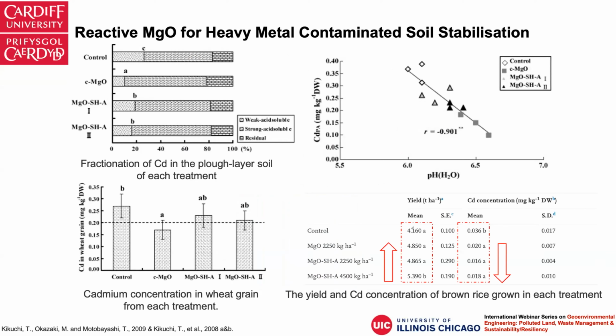This is quite an important one conducted by a Japanese group. So this study shows that using reactive magnesia as a soil stabilizer or soil amendment does not just reduce the weak acid soluble cadmium. If you are planting on top of the soil, the wheat and the rice, you see a very good reduction of these heavy metals within the edible parts of these plants. So the cadmium in the wheat grains is decreased, the yield of the rice increased significantly, and the cadmium concentration in the rice has decreased significantly after application of reactive magnesia.